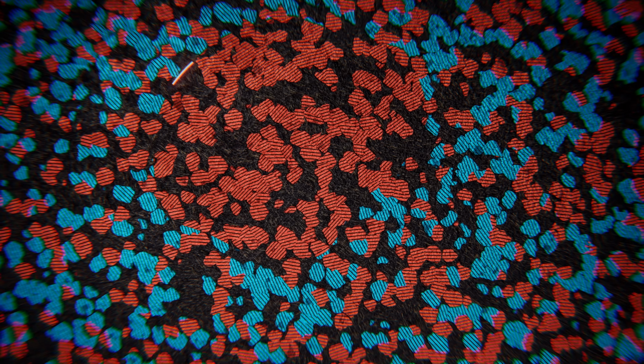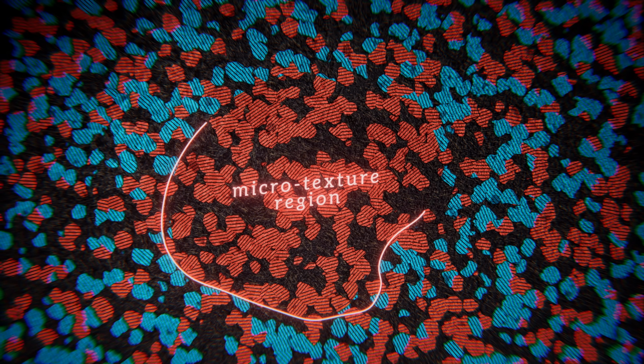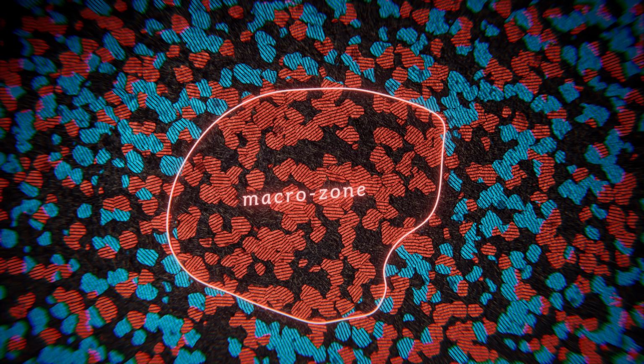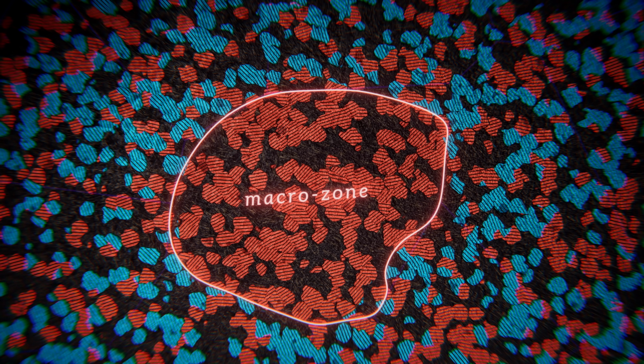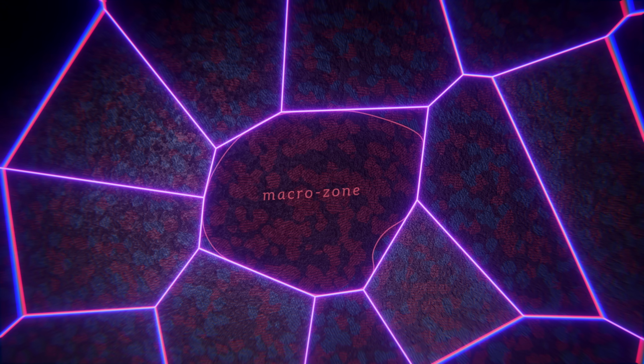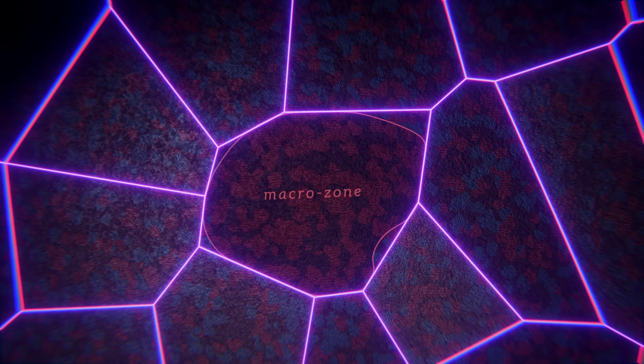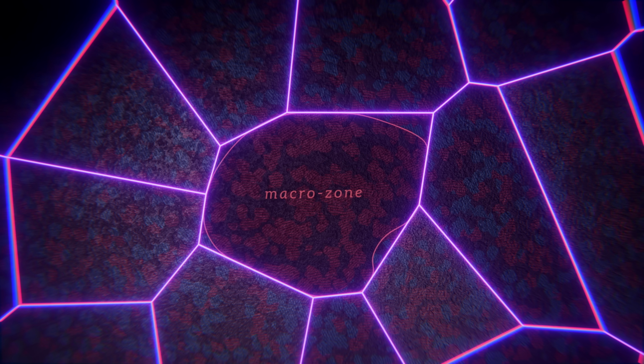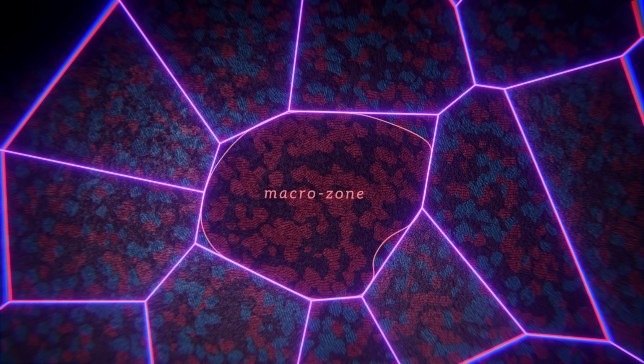The redistribution happens everywhere, so no single region accumulates too much stress. But the danger arises when the material contains a large cluster of similarly oriented grains, forming a so-called microtexture region, or macro zone. These regions can form when groups of alpha grains inherit similar orientations from the larger prior beta grains they formed within, and deformation applied during forging isn't sufficient to fully break up and randomize these orientations.